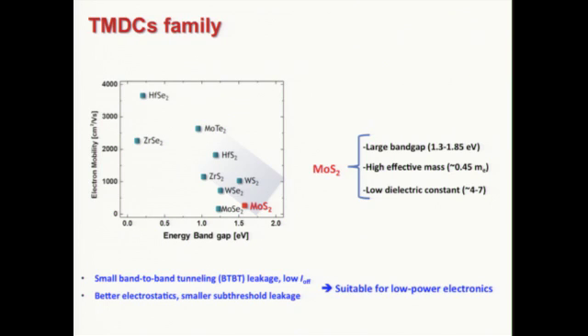So the transition metal dichalcogenide family is a rich family of semiconductors. We have both p-type and n-type semiconductors, perfect for CMOS application, with different energy band gaps and different electron mobilities. Here in this work, we are using molybdenum disulfide, which has a large band gap, a high effective mass of about 0.45 electron mass, and a low dielectric constant of about 4 to 7, depending on the number of layers. These properties are perfect for low power application because a large band gap and high effective mass would lower the off current in the transistors. Especially the high effective mass basically suppresses direct source-drain tunneling. And the low dielectric constant helps us to further improve the gate electrostatic control over the channel.